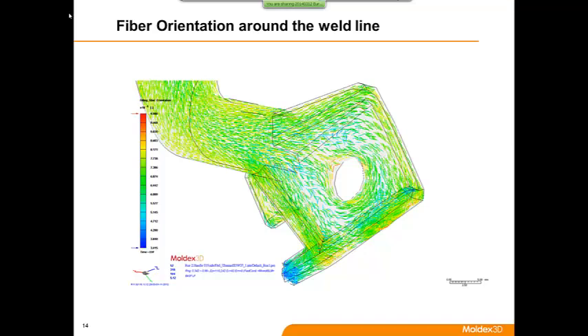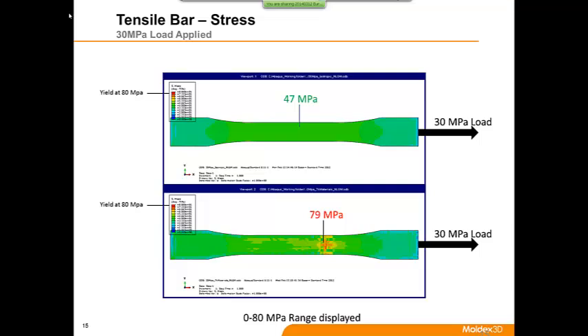So if you are doing some structural analysis, if you don't take this kind of anisotropy into consideration, you will falsely overpredict the strength of your part. But through this kind of simulation, later on you'll find out you actually did have a weak spot surrounding that circle. That's due to the fiber orientation.